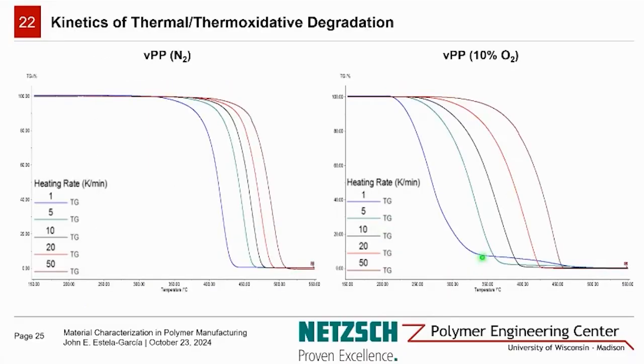On this slide, we appreciate the TGA results of the virgin polymer with various heating rates with respect to both the inert on the left and oxidative environment on the right. When we're comparing the results of the thermograms, this allows us to observe the stability of the polymer being heating rate dependent. Due to a polymer's poor thermal conductivity, higher heating rates create larger temperature differences within the material, and this shifts the thermogram to the right.